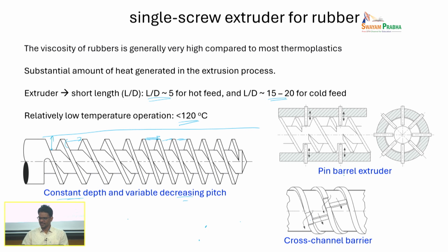Sometimes there are extruders in which there is a barrel with fins, okay. So you see that this is the barrel on the top and bottom, and there is some provision set here to restrict the flow conditions, okay. There are fin-like structures on the inner wall of the barrel, and then you have a screw rotating at a certain speed, okay. So this is called a pin barrel extruder, especially for rubbers. This shows the cross section of the same thing. So these are all the fins that are protruding from the inner wall of the barrel, okay. So instead of the barrel being hollow, you basically have baffles and pins coming radially inward, okay. But you can see that it is placed in such a way that the screw does not break them.